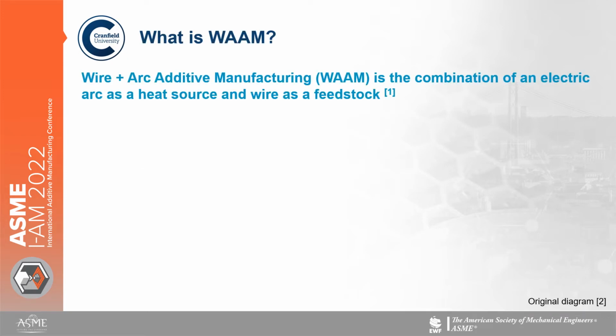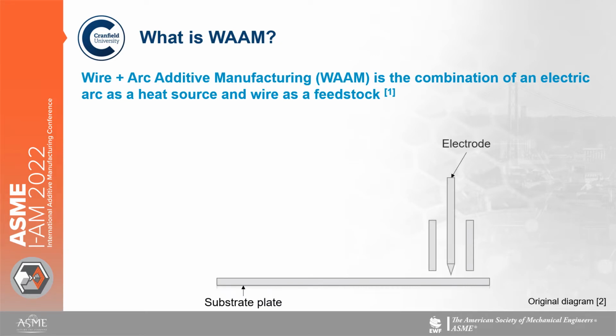So what is WAAM? Well, WAAM is the wire plus arc additive manufacturing process, which is a combination of an electric arc used as a heat source and wire as a feedstock. So we have our substrate plate, we have our electrode, which is our plasma welding torch in this case, as well as our wire feeder, which feeds the wire directly to the torch. In this case, we also have a trailing shield, which is providing extra shielding for our deposited material.